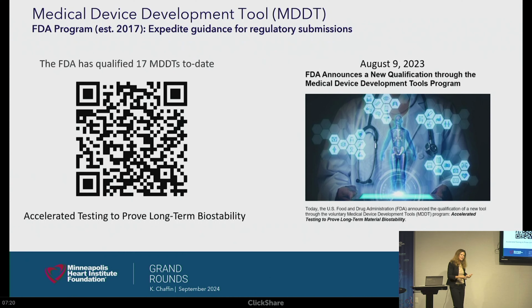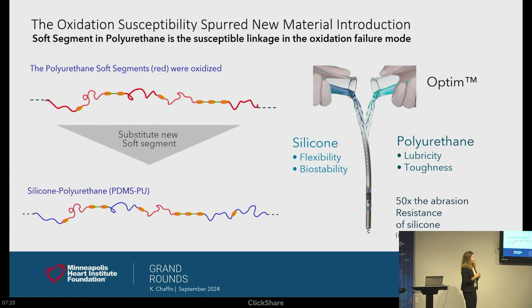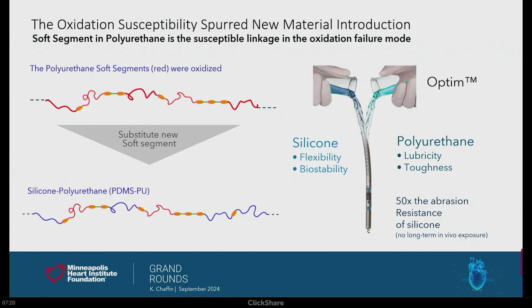But just because you have a standard doesn't mean the industry believes that this works. So let me go through some of the data that I did in getting this medical device tool qualified. So let's go back to polyurethane and that oxidation, whether it be environmental stress cracking or MIO. A tremendous amount of work was done in the industry to understand where those reactions were happening within that polymer backbone. And so polyurethanes are made up of soft segments and hard segments.